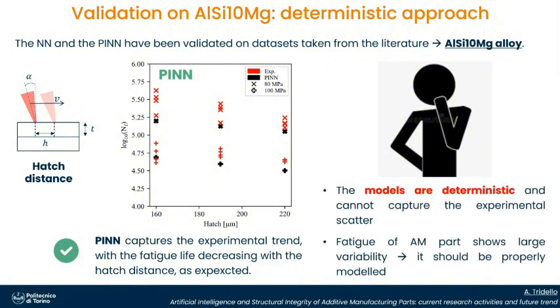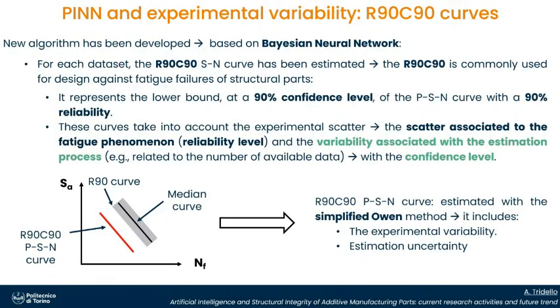The models are deterministic, okay, and cannot capture the experimental scatter. But the fatigue life of additive manufacturing parts show large variability, and this must be taken into account. We cannot design by taking into account a deterministic value, okay, or a median value. So we have developed a new algorithm, and for each data set, the R90C90 curves has been estimated. This curve is commonly used in industrial practice for the design against fatigue failures. It represents the lower bound at a 90% confidence level of the PSN curves with a 90% reliability.